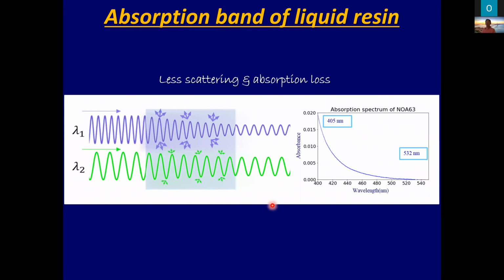And we want to reduce the scattering loss and absorption loss of the light field inside the polymerized matter. We replace UV light by visible light. Yeah? So we decided to use a 532 nanometer green laser light source. The wavelength coincides with the cut-off value of the absorption band. At that moment, we can expect less absorption loss of the light field inside the fiber. Of course, longer wavelengths can reduce the scattering loss as well. Okay, we can extend the photopolymerized fiber by the laser light injection.